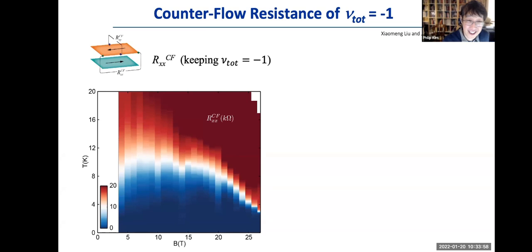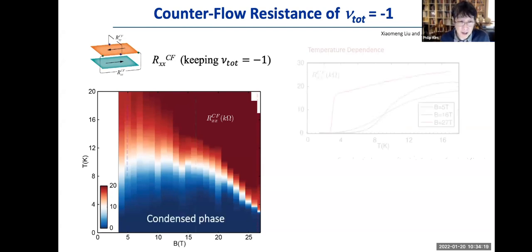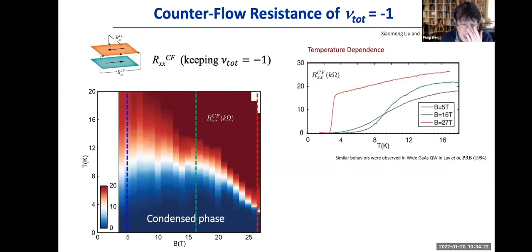So already you start to see that indeed we can realize this type of exciton condensation phase diagram, simply because in this graphene quantum well, since you put these two quantum wells very close, the energy scale is much larger, and you start to see that this type of phenomenon occurs at tens of Kelvin rather than millikelvin temperature ranges. That's exciting. But the more interesting part is when we look at the transition behavior at different magnetic fields, especially at high magnetic field, where you have a lot of exciton density such that the transition appears like a BCS type of transition.